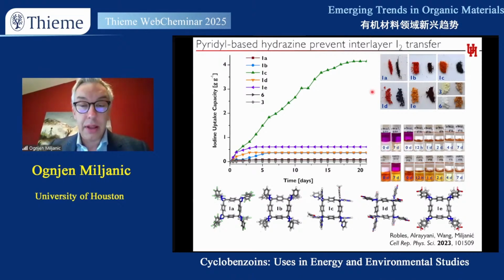And so if you think about nuclear reactor vessels or waste storage vessels, they are coated with a nuclear paint to prevent simply chemical corrosion of the steel vessels. But this paint, because it's basically vitrified glass, still has residual solvent, which radioactive iodine will iodinate, creating volatile iodides, which are both carcinogenic and radioactive now, and they also lead to cracking of this paint. And so we are now talking to the Department of Health, and they are expressing interest in this material as a potential binding platform for iodine.